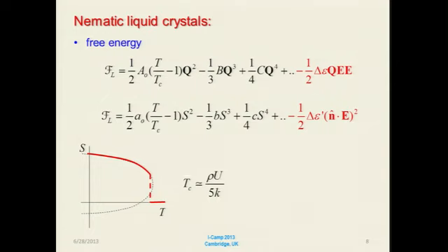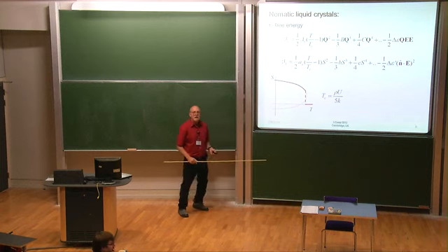One is that if you look at molecular theories, this critical temperature is proportional to the number density of mesogens. And so we have already heard about this from Mark and others. So if you dilute or increase the concentration, you're changing Tc. And if you dilute and you reduce Tc, that's essentially the same as increasing the real temperature.